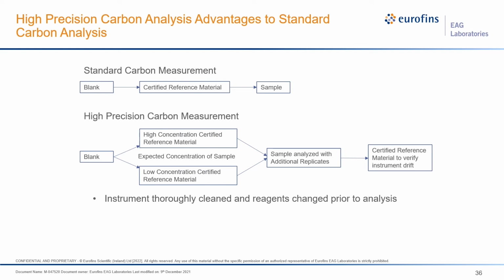After that, we do more replicates for sample than we do for standard method. The last step involves using a reference material with concentration near to the measured concentration in a sample. This is done to verify instrument drift, and if we detect an instrument drift, the entire method is repeated. For comparison, the standard carbon measurement analysis for a sample can be completed in, let's say, 30 to 40 minutes, while high precision method takes more than 2 hours to accomplish one sample.